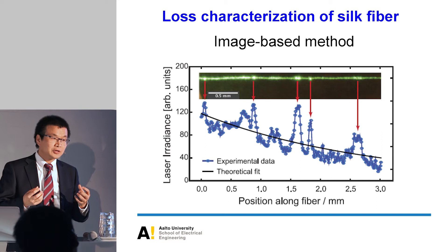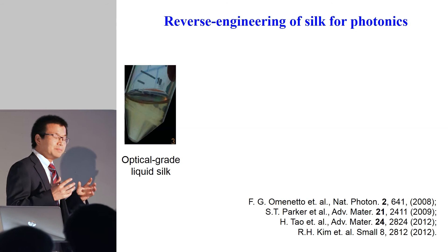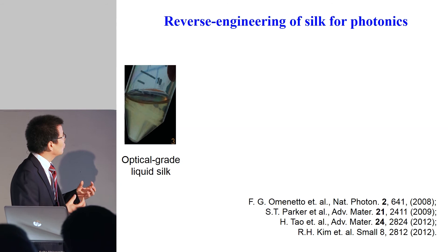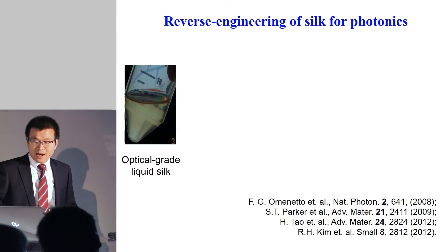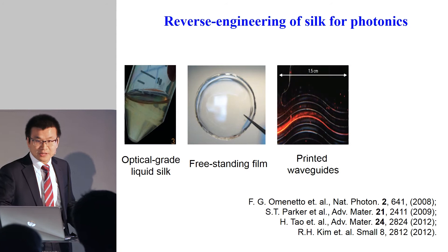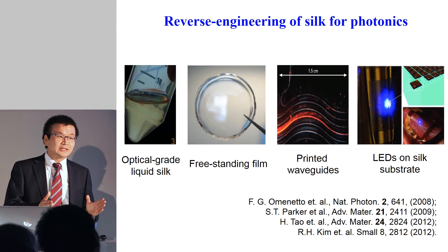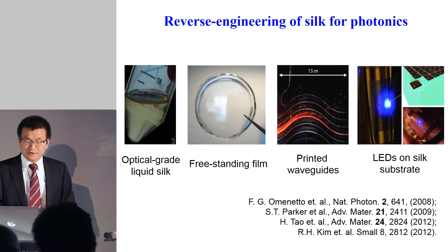To make high-performance photonic devices, you need a reverse engineering process. What other researchers do is dissolve the silk cocoon into solution to make liquid silk, then drop-cast it to make a very thin film. After that, you can use lithography to pattern it, or print it if you have a printer. If you want to turn a passive device into an active device, you can combine silk with different hybrid integration techniques — for example, placing a light source on the silk substrate.